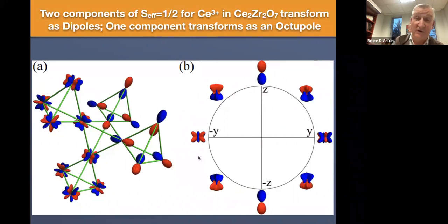Of course, this is a cartoon, and it's just meant to give you some idea that you can have either interacting magnetic dipoles on different sites, or interacting magnetic octupoles on different sites, and it all depends on whether the interaction between the Y component of this spin-a-half degree of freedom is dominant, or whether the interaction between the X and Z components is dominant. So there's going to be a whole bunch of different possibilities for the ground states of these materials, but they can either be dominated by their dipolar degrees of freedom or their octupolar degrees of freedom.